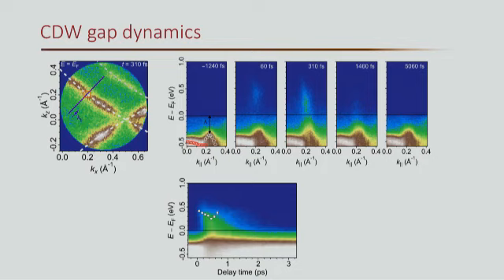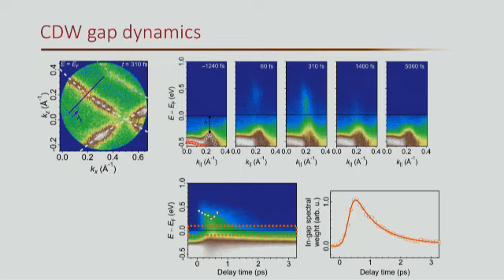To estimate the time scale from ARPES data, for example how the gap closes and reopens, even though we couldn't fit the gap very accurately, we can use the spectral weight around EF as a proxy to measure how much spectral weight filled in the gap, and then how much this spectral weight relaxes back to its equilibrium position. So what we're doing here is integrating all the spectral weight within these energy windows, and we see, first of all, within a few hundred femtoseconds, a filling in of spectral weight, which is representative of a partial closing of the gap. Then quickly the gap reopens, which is represented by the relaxation of this spectral weight in the gapped region. And of course, we can fit this with a single exponential decay and extract the time constant.